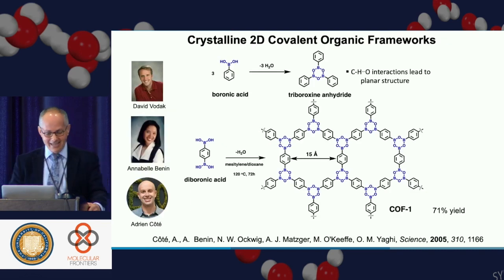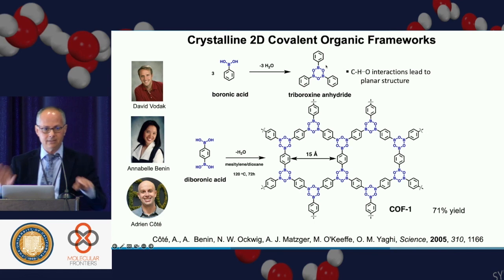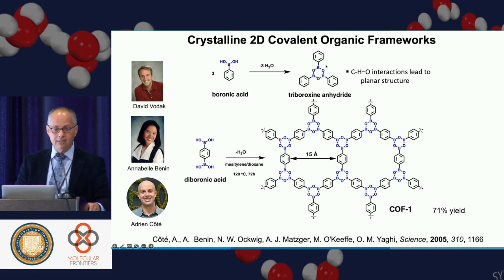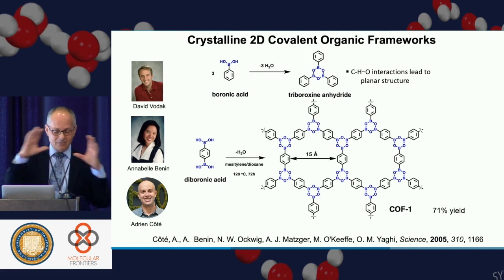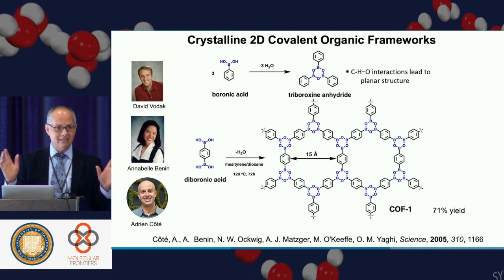So this Annabelle was the undergrad that made this work. And she zoomed in on this molecular reaction. You see here this boronic acid. This is known. You can dehydrate boronic acid and make this triboroxine anhydride. This is a flat molecule. This is a planar molecule because there is a weak CHO interaction here, a weak hydrogen bond that makes the molecule planar. And from a reticular chemist point of view, I can take those building units and imagine that I'm reticulating them, and I can calculate the powder diffraction for them.